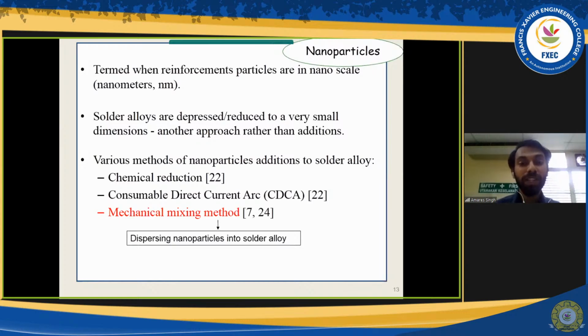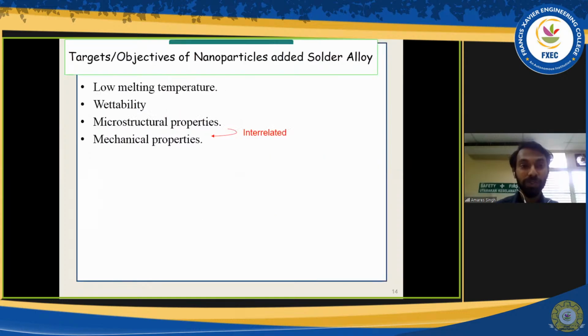Then we come to the conventional way, the mechanical mixing method. I'll be explaining this method later. It's basically intentionally putting in, or dispersing, the nanoparticles into the solder alloy. Of course, being nanoparticles, the scale must be in nanometers, because even if the particles are in micro scale, the influence that they impart to the solder alloy is different from when they are nano scale. So it's very important to make sure the particles are in nano scale.